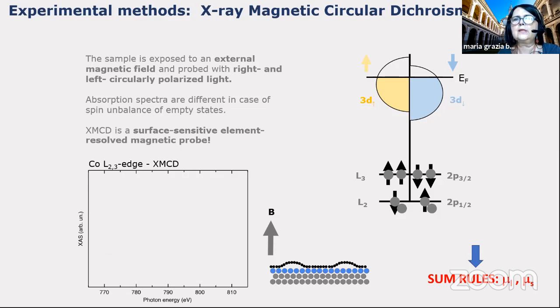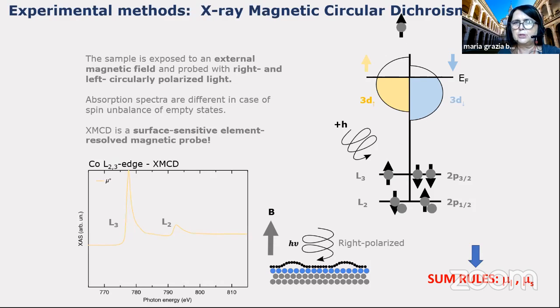The first step is to characterize the magnetic activity of the system. So we use X-ray magnetic circular dichroism. This technique is very powerful because if the sample is exposed to an external magnetic field and probed with right or left circularly polarized light, we can have an absorption spectrum. This is the absorption spectrum of cobalt, these L3, L2 edges. So from the 2p states, we are going to the empty states.